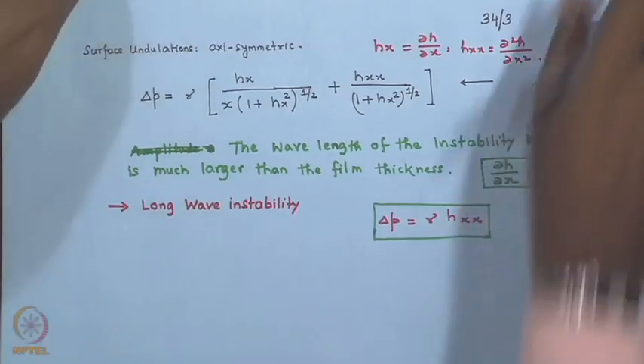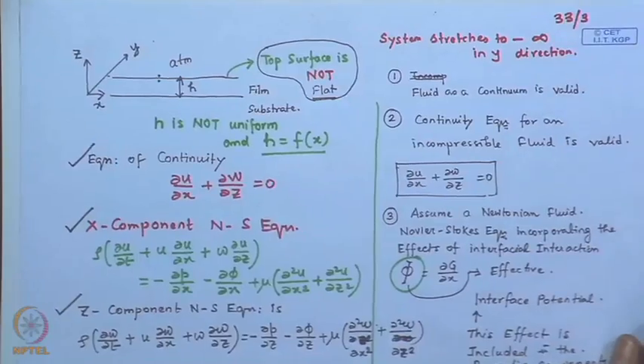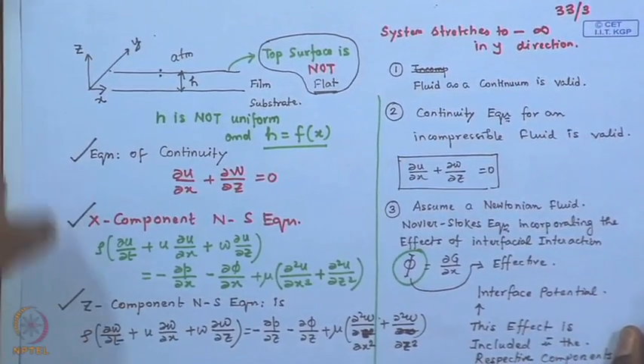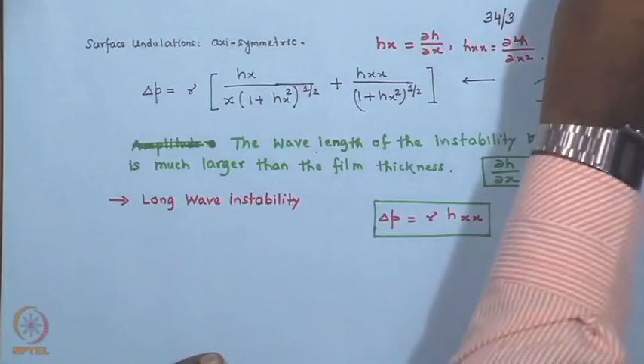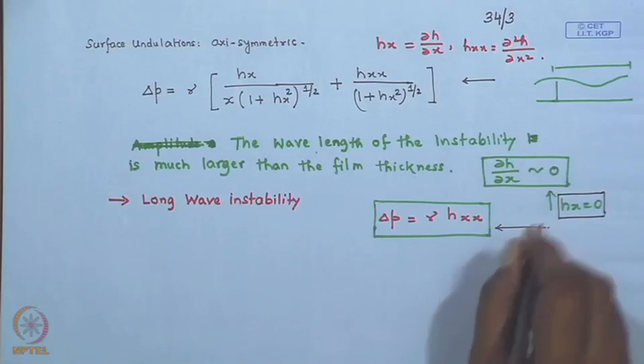The condition of long wave instability, which in simple words means that the wavelength of the instability is much higher as compared to the film thickness, results in very relaxed slopes or curvature of the film surface, which means that del h del x is approximately 0, and you plug it in to get this form of the Young-Laplace equation. So, along with the 3 governing equations which we have listed, we have a 4th equation which we will be needing to use.